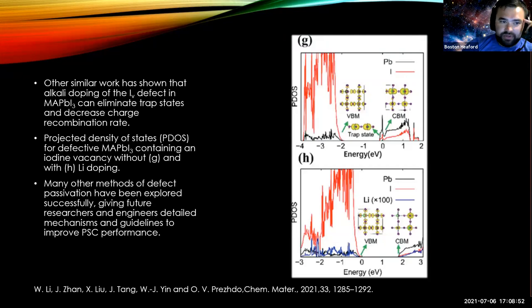And then even more similar work has shown that alkali doping of the iodine vacancy defect in methylammonium perovskites can eliminate trap states and decrease the charge carrier recombination rate. And these graphs show the projected density of states for the defective perovskite containing an iodine vacancy, without and then with lithium doping.